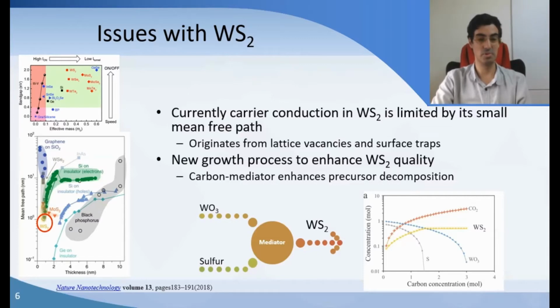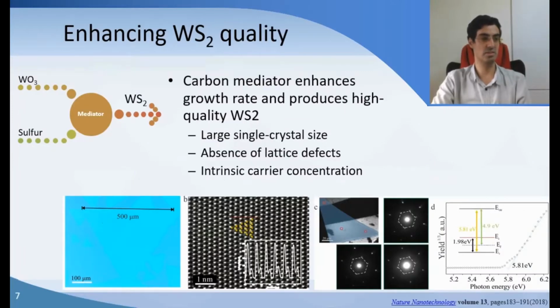But that's because WS2 is actually fairly defective. And so we have introduced a new type of growth where we're providing a mediator to take the two precursors necessary for growing WS2 and improve their combination into the final product. We're using carbon because carbon helps in the reduction of tungsten oxide and stabilizes the supply of suitable precursors. And the result is very promising. We see that we can generate very large grains of WS2, and these are indeed single crystalline. And if we zoom in, we don't observe any lattice defects.